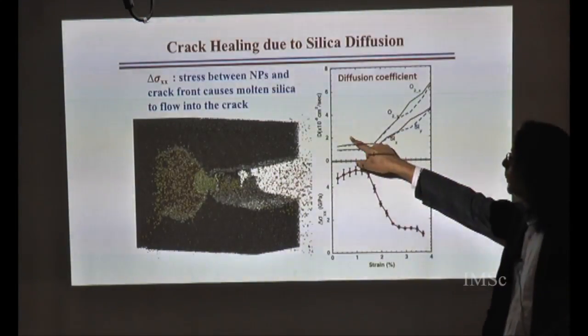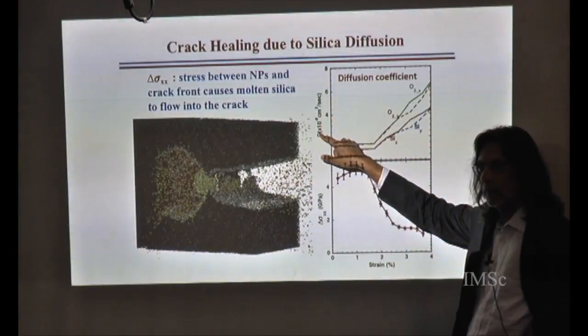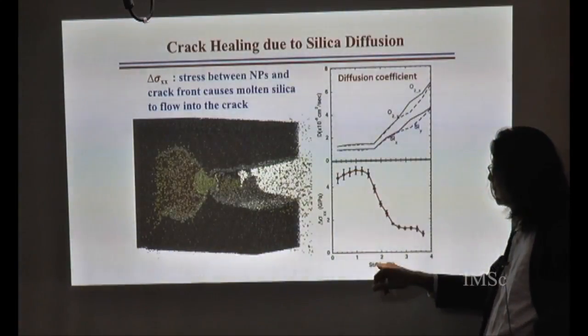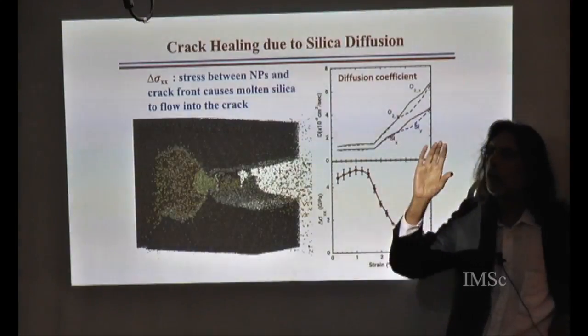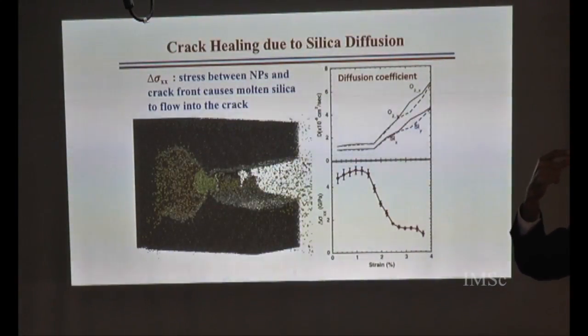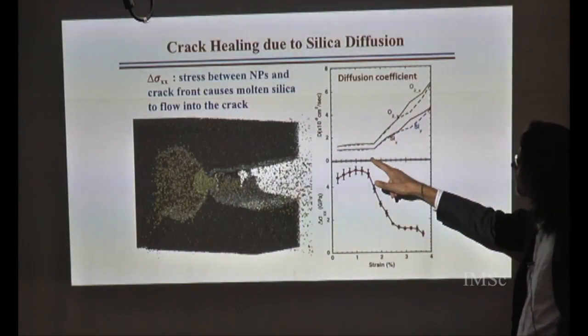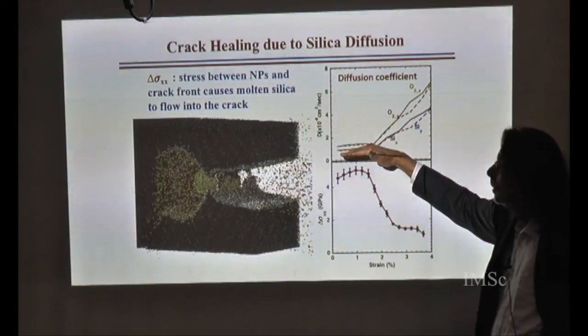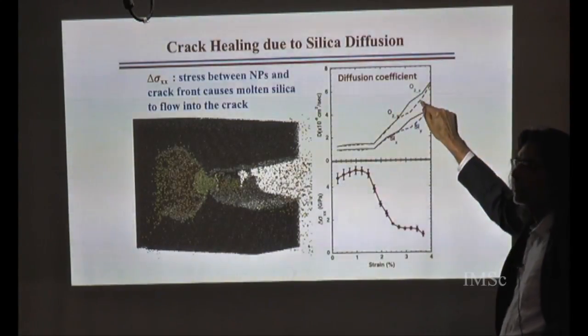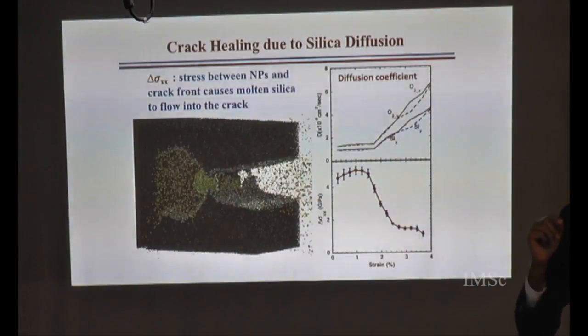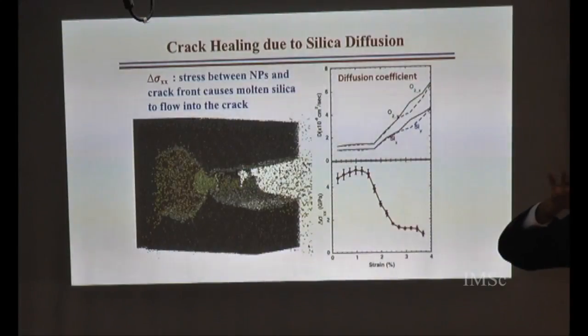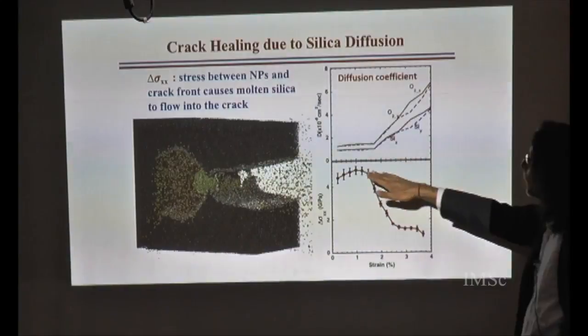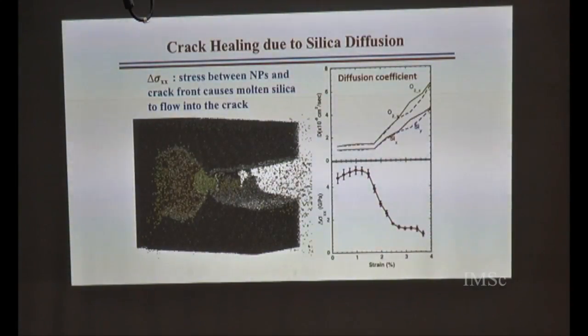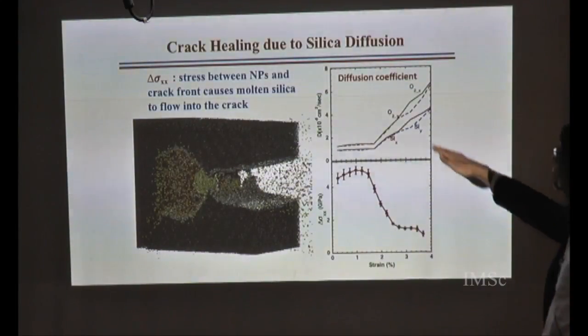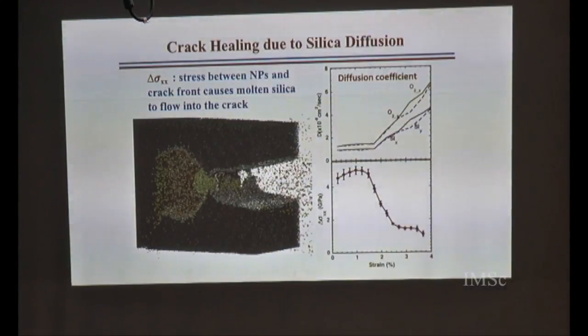Here I'm plotting the self-diffusion coefficient of silica, silicon and oxygen both, as a function of strain. Up to 2%, the distance between the nanoparticle and the crack was not much affected, but after the strain exceeds 2%, the self-diffusion coefficient for silicon and oxygen jumps, and then you can see a rapid increase. This is the cause of healing of the crack in alumina. Silica is in fact diffusing into the crack and repairing it. We can then calculate the stresses between the crack and the nanoparticle, and what they are doing to the diffusion of silicon and oxygen. The message here is that it's really silicon and oxygen diffusion into the crack that is stopping it.